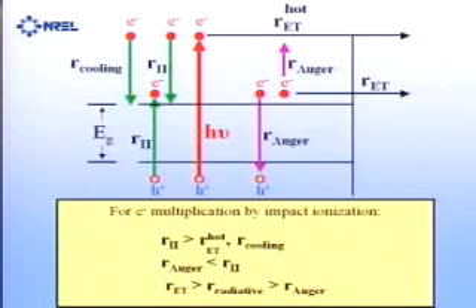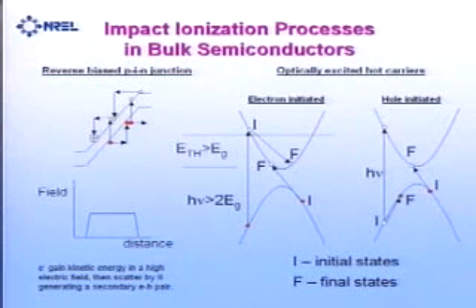And it has to compete with the inverse processes where you have 2 electrons, one of which will combine with the hole and give its energy to the remaining electron and excite it. So that's the inverse of this, or this is called forward Auger, and this is the inverse Auger. Now, this process was examined for bulk semiconductors, but in addition to balancing energy, you have to balance momentum. And because of that, you can't drive the multiplication with just a band gap photon. And you have to have the change in the momentum of the electron balance that for the photon. So you need a much higher energy.